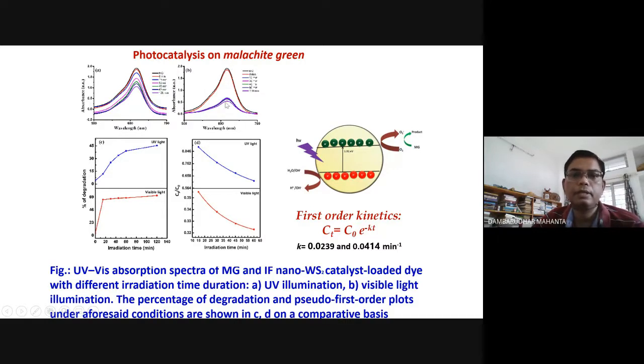So there we find that there is a drastic reduction. So this has been shown here in the panel below, figure C. The percentage of degradation, as you could see, in case of UV light, is slowly increasing. But in case of visible light, it was very fast. At 20 minutes, it goes up to 69%, and up to 2 hours or so, it goes up to 70 to 73%. These are the rate constants calculated for different materials.